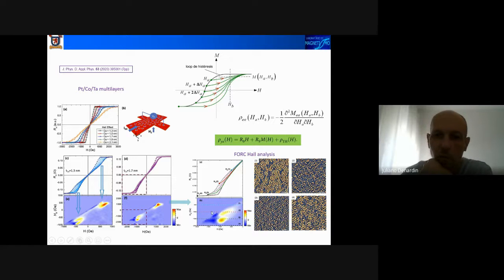But if we go to the saturation of the sample, HR4, we come back to the stripe domains. That means that you can find appropriate reversal fields that you can apply to the sample, come back to the zero field, and observe skyrmions. The skyrmions nucleate and stay stable in zero field for this kind of sample, and you can discover what fields are these appropriate fields by doing the first order reversal curves in Hall effect or in magnetization.